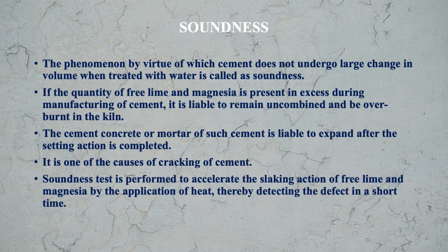Now the soundness test is performed to accelerate the slaking action of free lime and magnesia by the application of heat, thereby detecting the defect in a short time. Because otherwise, in the natural process, this defect will take a lot of time. So by accelerating the slaking action, we can detect this in a short time.